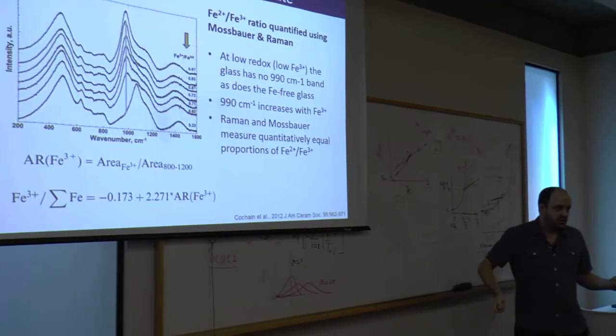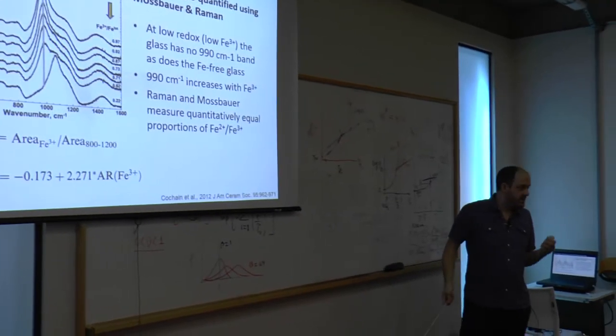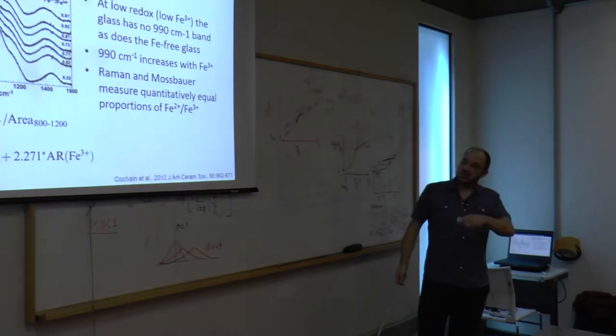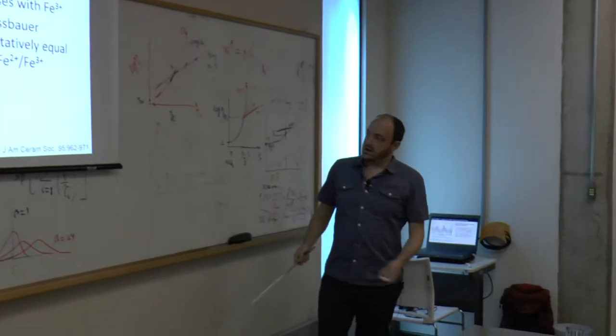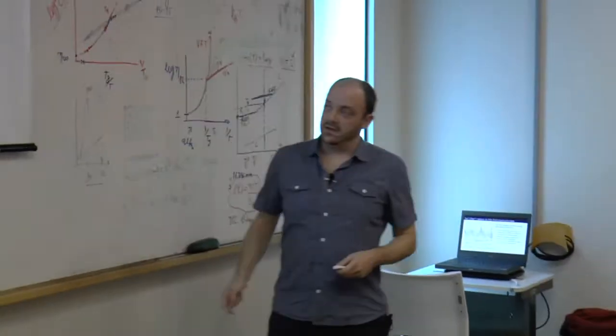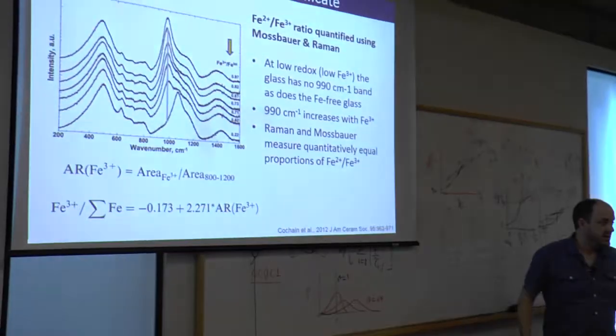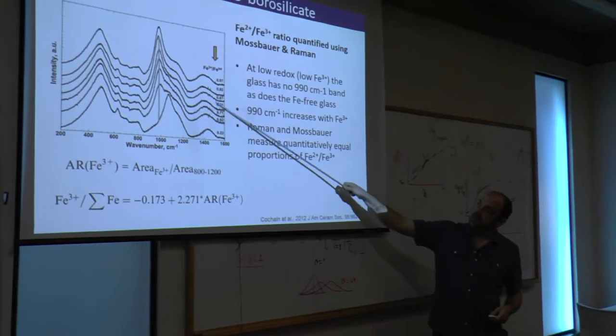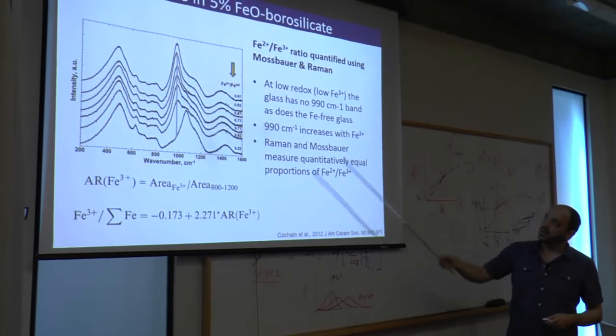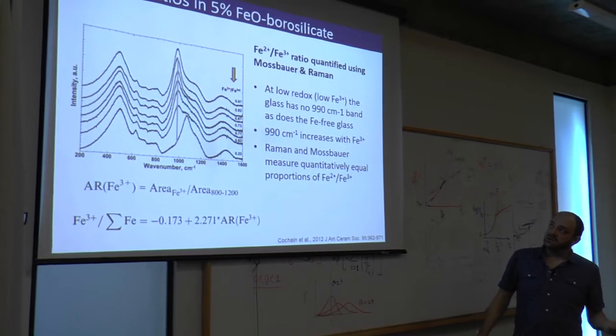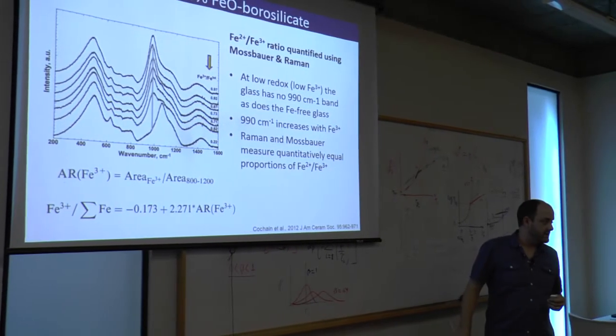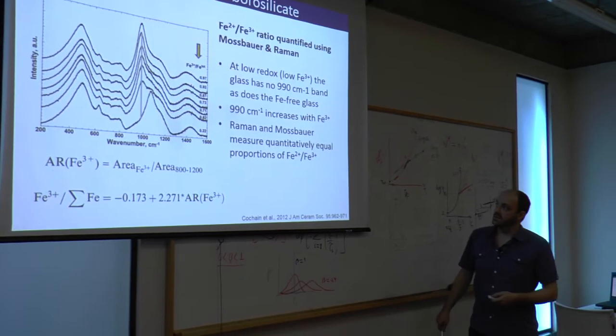So you have strong bands that overlap the Qn species, and we are going to talk about curve fitting at the end. But you need some sort of model, and again, some sort of normalization to actually compare spectra with quite different compositions. And in this case, Raman is very sensitive to the redox of iron, and we can quantify this.